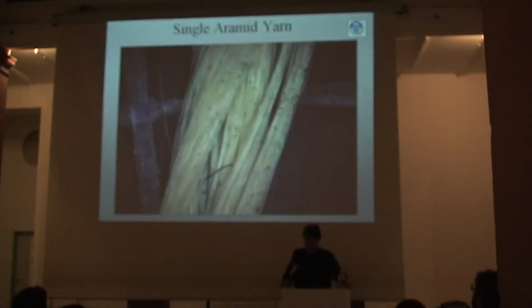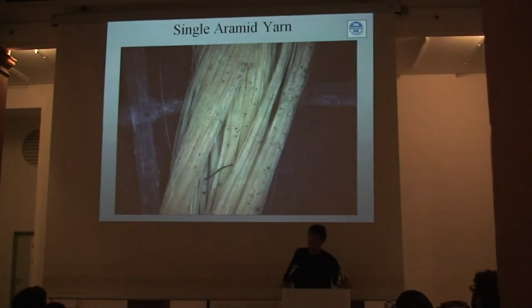And to take a step back and talk about what we call unidirectional or pre-preg or oriented tape, that's a photograph of a single aramid or Kevlar yarn taken underneath a microscope. So the characteristic of what you think about as an individual yarn or a fiber tow is that in fact it's made up of a lot of different filaments. So in this case, there's 3,000 filaments in this aramid fiber. So that's one individual filament. It's about 12 microns, kind of the size of a human hair.